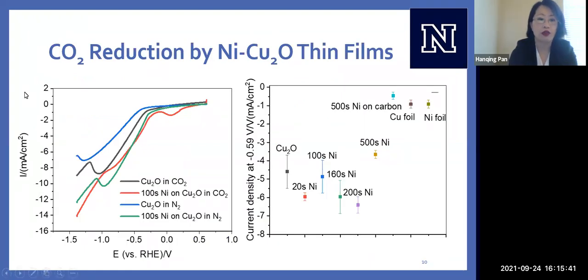And the first thing we can do is look at the electrochemical behavior of these films. So this is a linear sweep voltammetry, and we're just looking at how much current density is being generated as a function of voltage. And the 2 metrics we look at when we look at these linear sweep voltammetries is first onset potential. So where is it that our reaction is beginning to occur? So where is it that this line is increasing in slope? And also which catalyst is giving us the best or most current density?